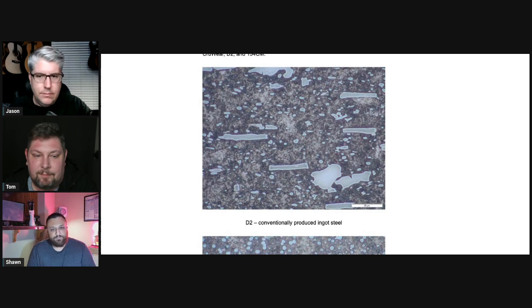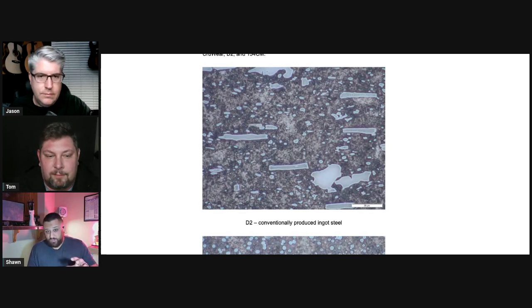But, for reference, a lot of PM steel carbides are pretty fine. A lot of them are well under 10 microns. A lot of them are well under the size of a red blood cell. But with these carbides, you can see they're incredibly large. And what we also see is they're elongated. They look like long sticks in some cases. They're all kind of going from left to right.